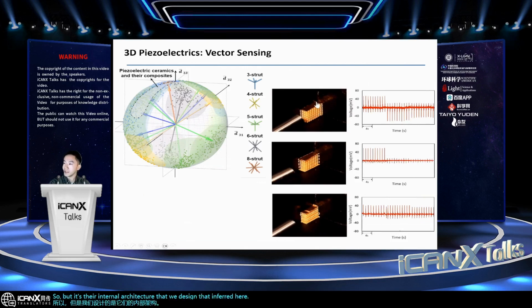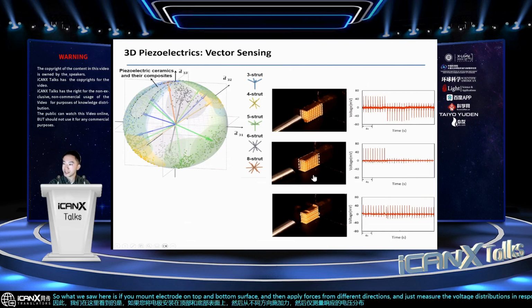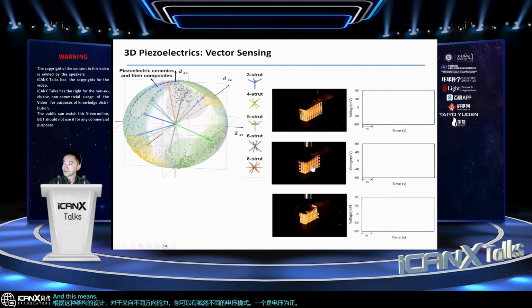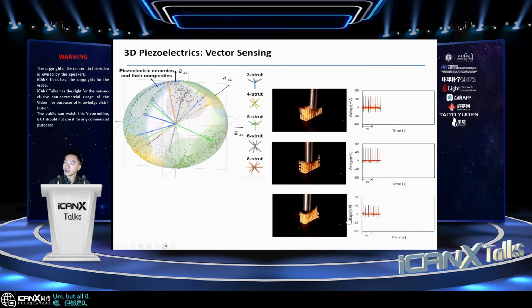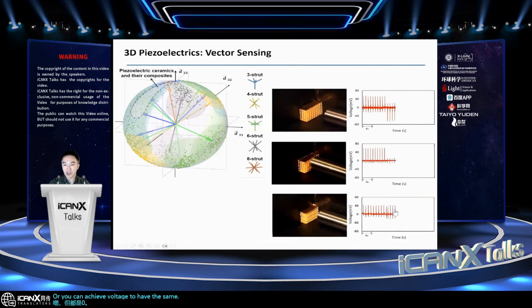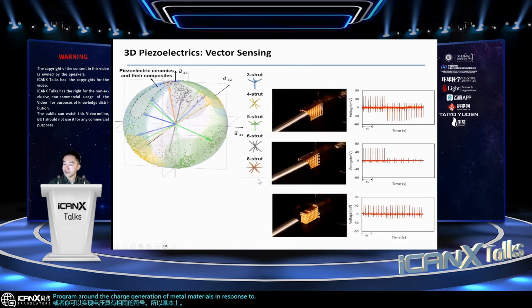So what we saw here is if you mount electrodes on the top and bottom surface, and then you apply forces from different directions and just measure the voltage distributions in response, what you observe is that based on the design of this architecture, you can have drastically different voltage patterns for forces coming from different directions. So one is the voltage being positive in one direction, negative in other directions. And this design shows that the voltage is positive in one direction, but all zero in other directions. Or you can achieve voltage having the same sign. So basically you can program the charge generation of metamaterials in response to forces coming from different directions.